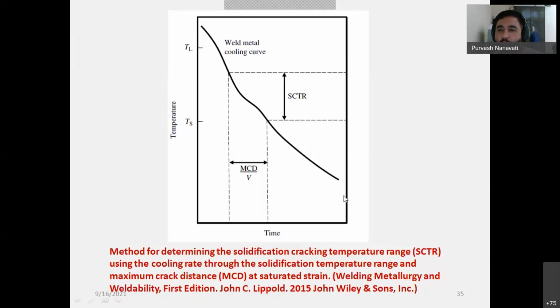TLTS. Now you see a cooling curve, right? You would literally see this is a cooling curve, because as soon as the weld joint is made, having calculated this MCD divided by V, the particular range, say 0.5 to 0.7, right? Most of the time this value. Now, if you project it on the cooling curve, you see a solidification cracking temperature range, SCTR, and most of the time you see it is between TL and TS, right? So you could figure out this SCTR by, say, multiplying the cooling rate with MCD divided by V.